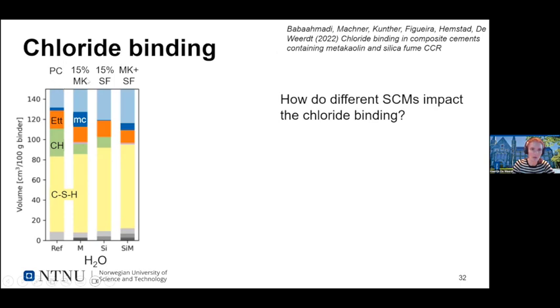So she had a reference Portland cement, a cement where she had replaced the Portland cement with 15% metakaolin. She used 15% also silica fume and a combination of metakaolin and silica fume. And what we see in this figure is the volume of hydrates per 100 gram composite cement for these 4 systems. And what we can see for the Portland cement, as we've seen earlier, we have CSH, Portlandite, ettringite, and some monocarbonate. And when we replace 15% of the Portland cement with 15% metakaolin, we have a reduction in the Portlandite content, so the pozzolanic reaction. We have some more CSH, and we get more AFM, as we've seen earlier.